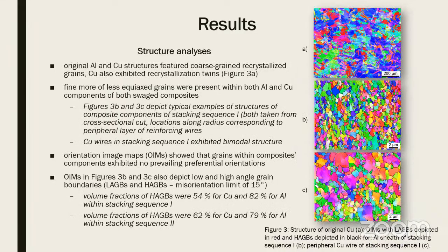Here in these figures we can see the structures. The original aluminum and copper structures both featured coarse-grain recrystallized grains. We can see an example of the original structure of copper in figure 3a. There are also some recrystallization twins, so both the original materials were in the recrystallized form.